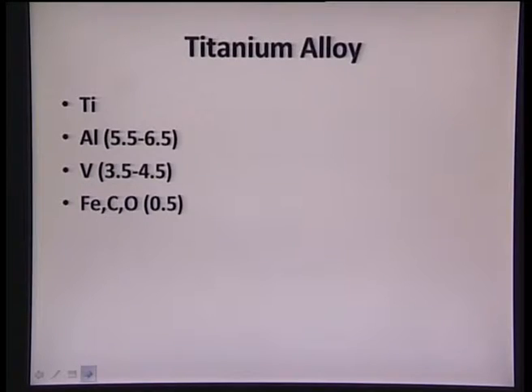Coming to the titanium alloy, generally titanium itself is not that strong in nature, so it also needs certain reinforcement, because titanium is a single phase material, and if we start making it a dual phase material, so instead of having only the alpha or HCP phase, if we start inducing a secondary phase, we can also get strengthening from the secondary precipitate. Why? Because it will also impart an impediment to the dislocation motion. It can also generate some new slip systems which can be available for the slip to occur. So in that manner, it will enhance its ductility. So the processing part is basically enhanced. At the same time, the strength can also get enhanced because of the dual phase microstructure.